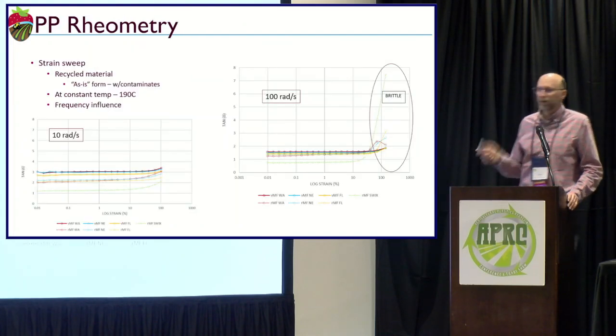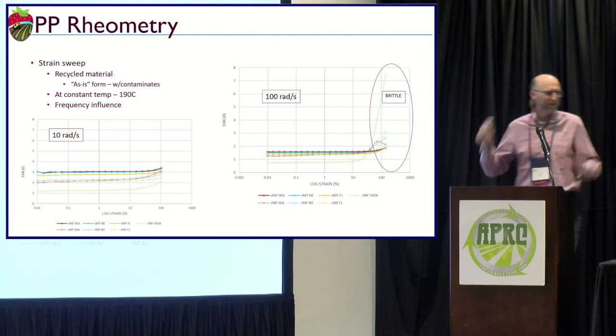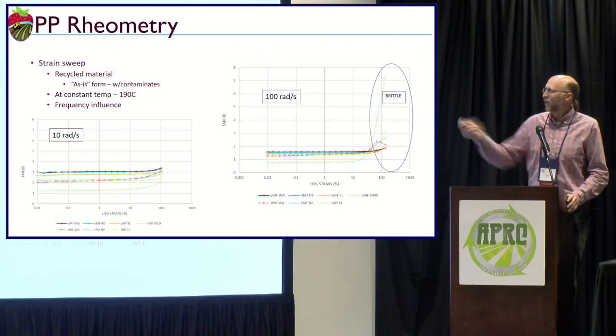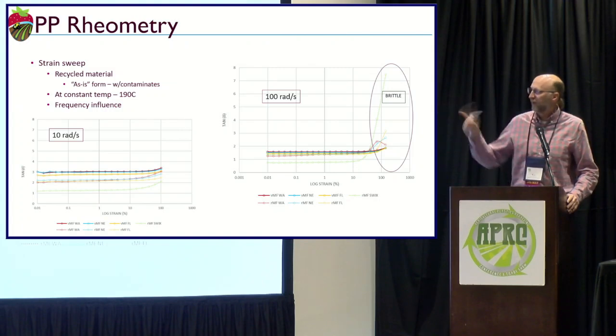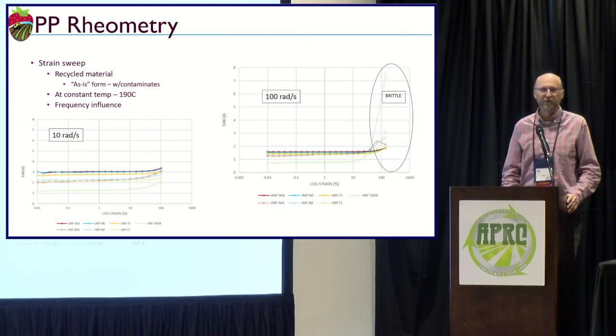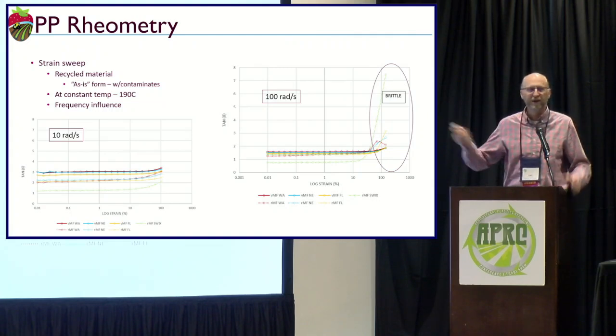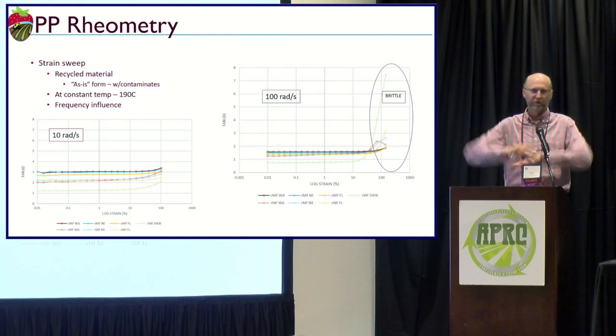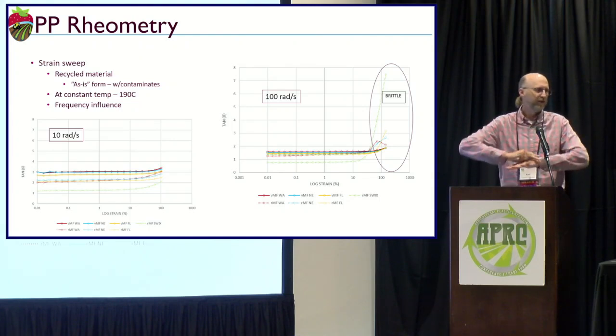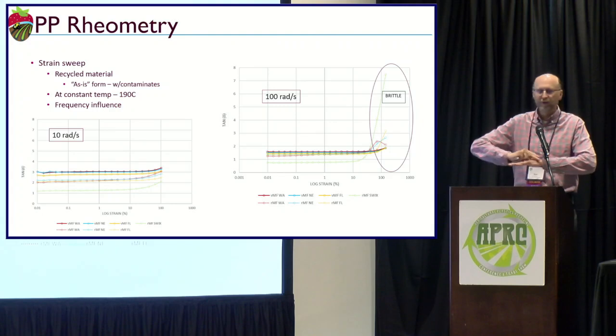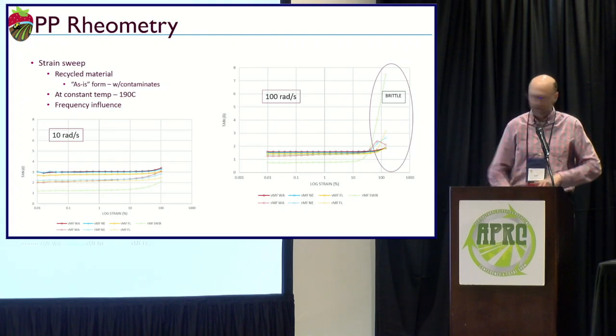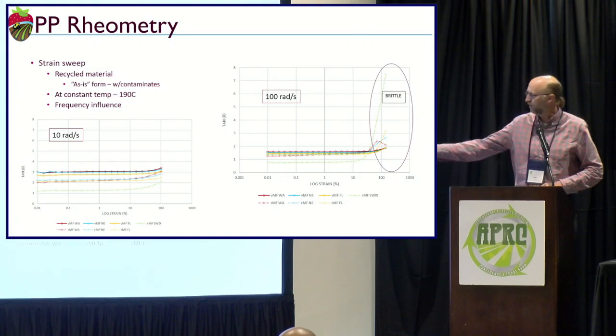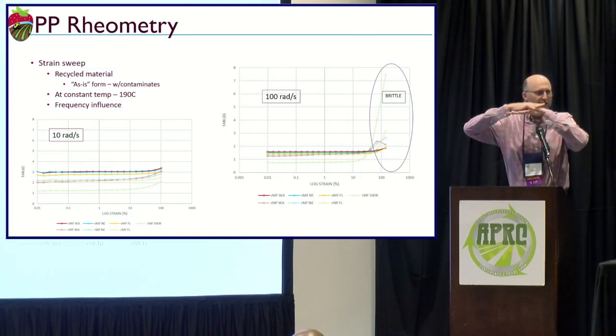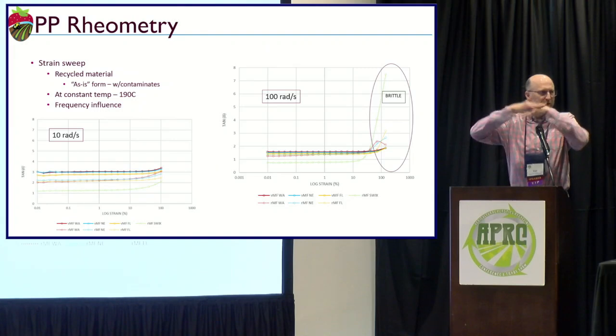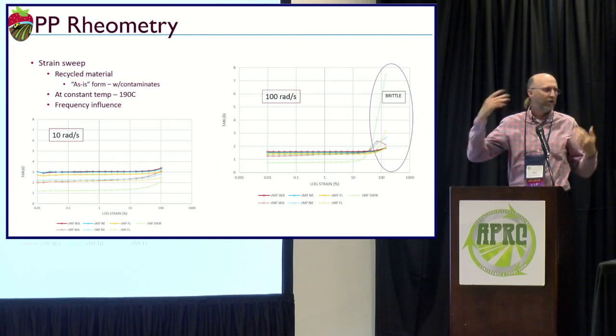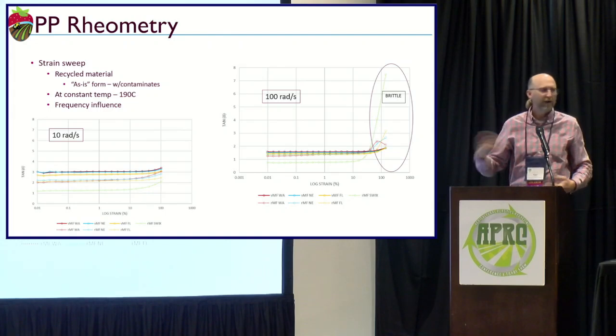If you look at this data, don't fall asleep on me yet. I know it's data, it's a curve, and it's busy. This is the as-is material, so it has a lot of load of materials in there. Look at the 10 rads per second, that's 10 radians per second. It's in a circle, so radians is how you measure the displacement, how much you're moving. 10 rads per second is relatively slow, and so you're spinning it. Your x-axis is your strain, how far you're spinning it. So 10 rads per second is going like this. 100 rads per second is going really fast, a higher velocity speed.